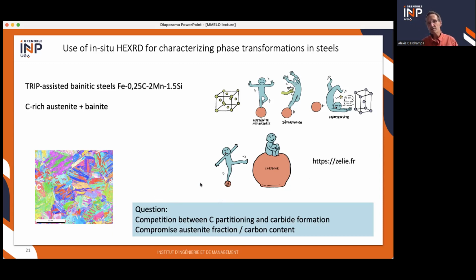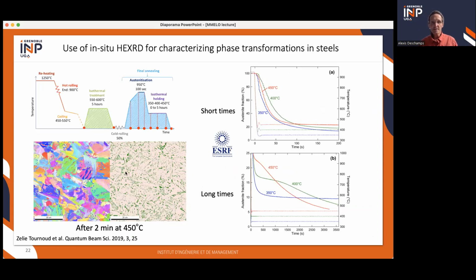So to know that, we could do some in situ X-ray diffraction. So basically, I won't discuss the whole process, but we're looking at the end part here, which is very simple: austenitization, and then isothermal holding at 3 temperatures, 350, 400, 450. And during this isothermal holding, you get some residual austenite that you can characterize at the end at room temperature. But of course, at room temperature, you're not looking at what was happening at higher temperature, because during the final cooling, you can have some martensitic transformation. So that's why you want to know really what's happening during the transformation.